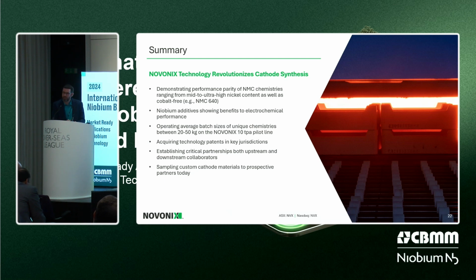What I've shown in the last few slides is that niobium can be used as an effective dopant or coating. And at least for the coating work, there are benefits to the electrochemical performance of the materials when put into a cell. I've also shown that we have our pilot line in Nova Scotia, Canada, so we are generating real quantities of materials. Our average batch size is between 20 to 50 kilos of powder, and we're making different materials all of the time going through our roller hearth kiln.